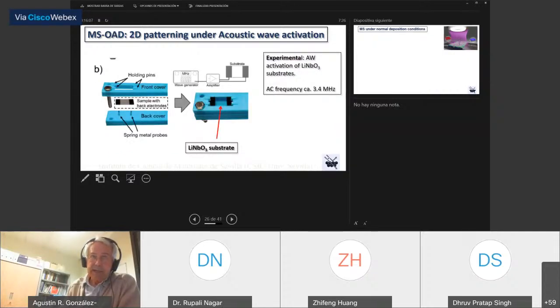Well, this is a sketch of the experimental device. We have a lithium niobate substrate with 2 electrodes. We have some pin here to produce the excitation. And in this particular case, one of the resonant frequencies of this lithium niobate piezoelectric crystal is around 3.4 megahertz.